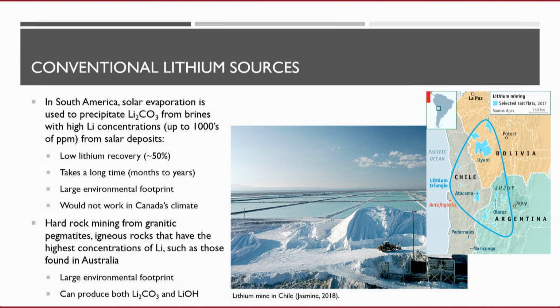And these brines then are sequentially evaporated, well, there's a lot of solar radiation in that region, to isolate the lithium ions and ultimately produce either lithium carbonate or lithium hydroxide, which are the two salts that go into making batteries. The problem here is it's fairly inefficient, about 50% efficiency. It takes many months to over a year to do this process. And you can see in the picture here, it's quite environmentally intrusive.